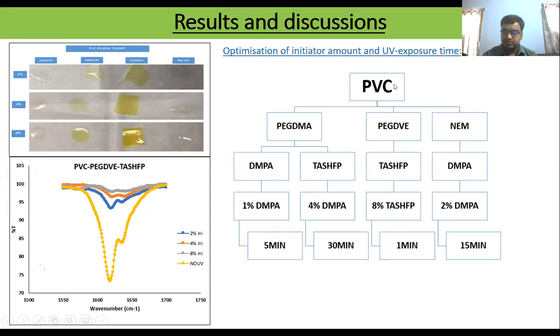So this is the result that shows this for PVC-based polymer. If we use PVC as a base polymer for membrane preparation, and we use PEGDMA as a cross-linking agent, and if you use DMPA, then the optimum condition will be 1% DMPA and 5 minutes of UV treatment. In PEGDMA, if you use TASHFP, then our result shows 4% TASHFP and 30 minutes. Similarly, we did it for PEGDVE. This is the optimal condition, 8% TASHFP and 1 minute. So this condition shows for the PVC-based polymer.